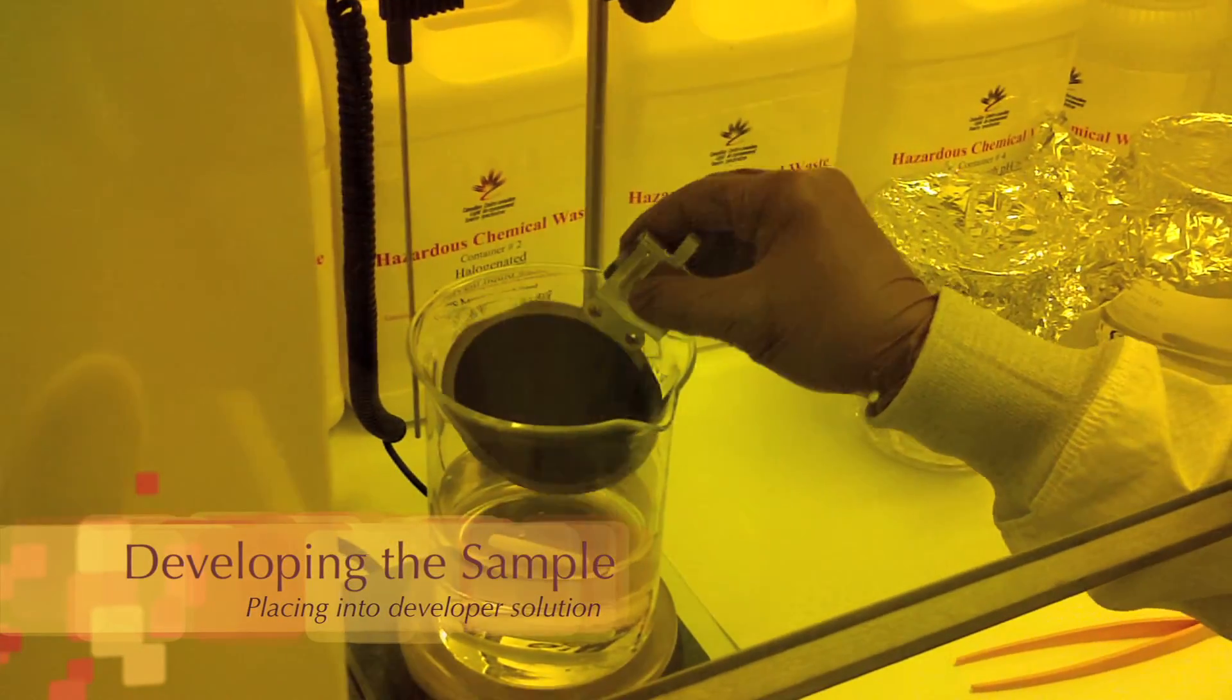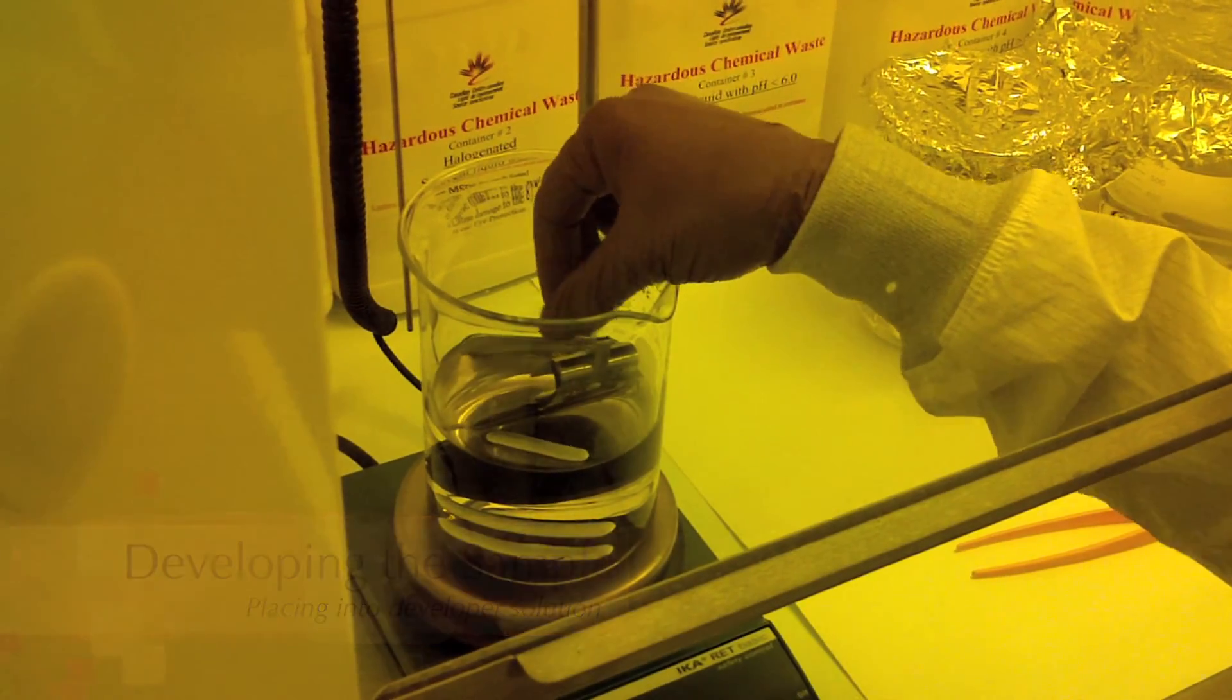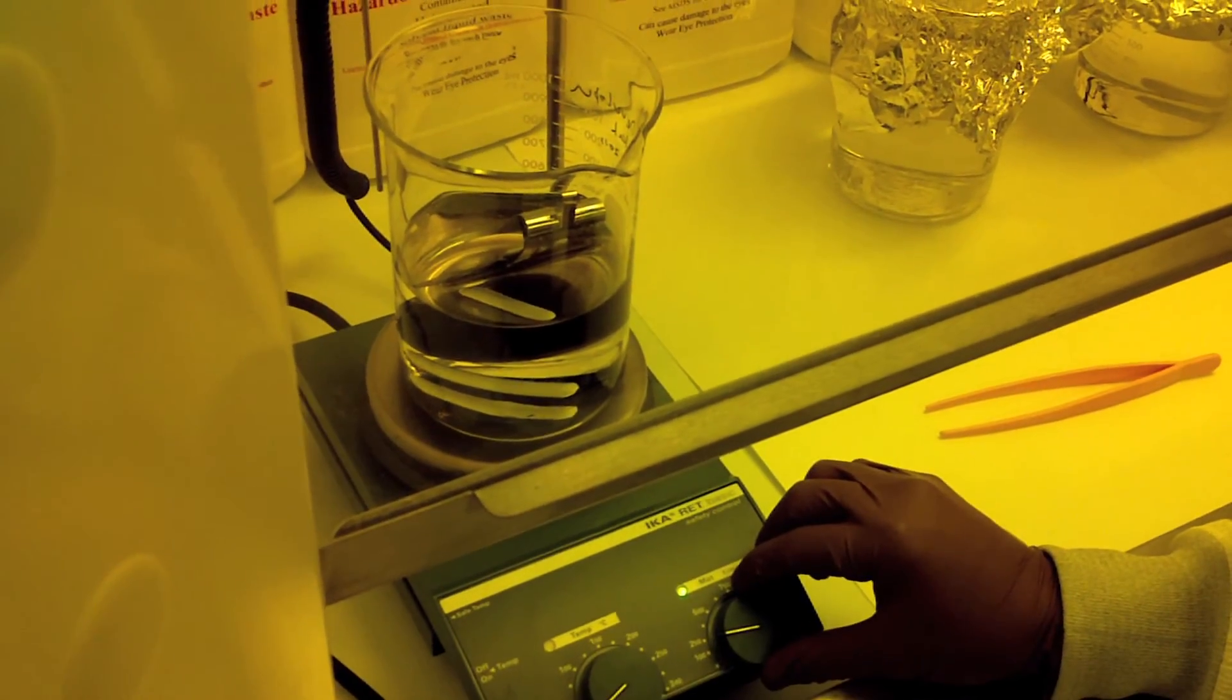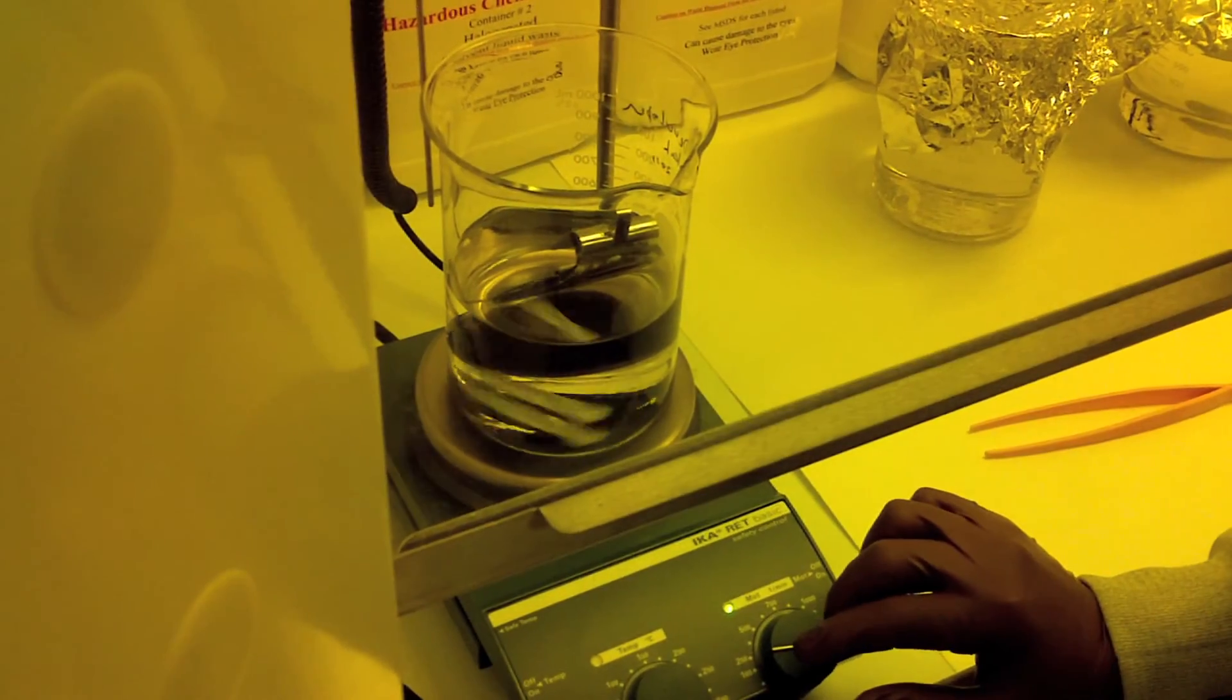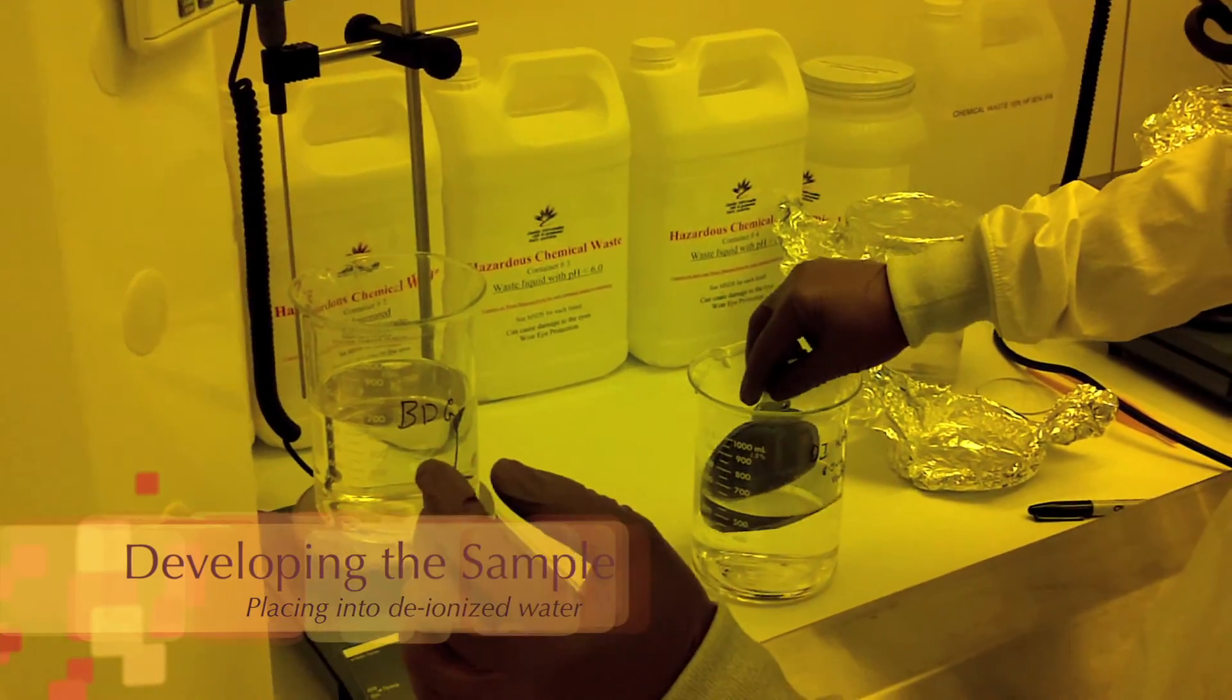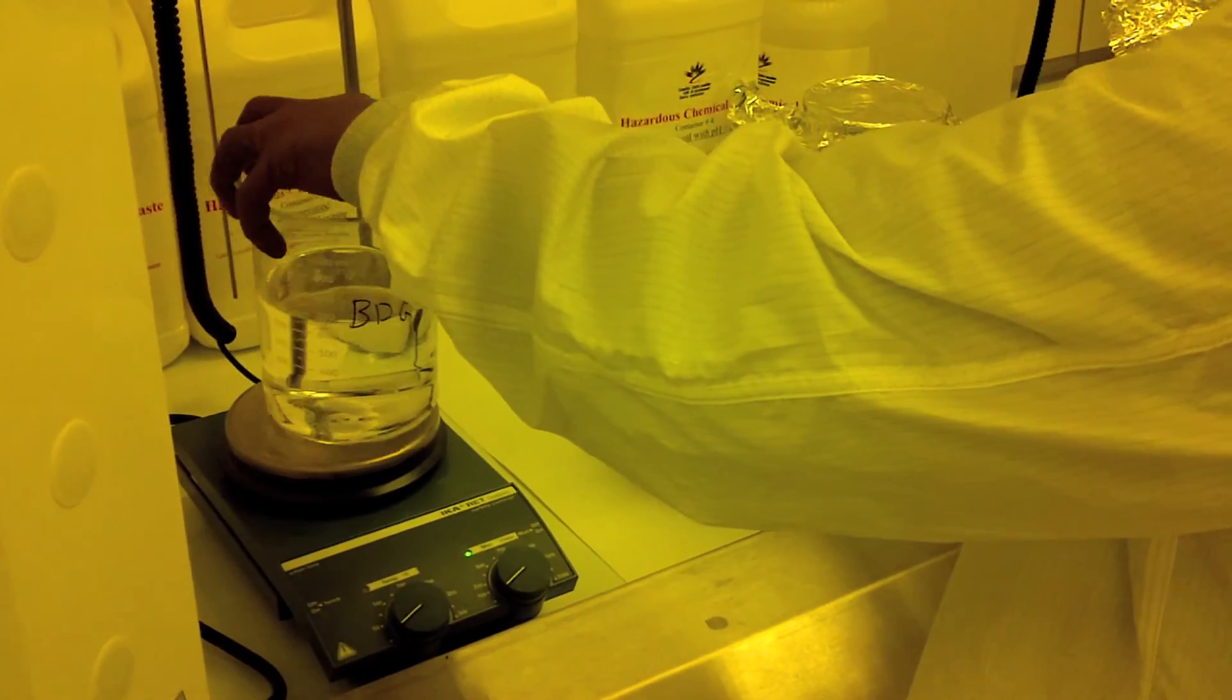Immediately after exposure, the sample is immersed in a premix developer solution to wash away the exposed areas of the resist to the X-ray beam. This process is time critical as the longer the sample sits outside after exposure, the harder it becomes for the exposed resist to be removed. The development process is finished by immersing the sample in a milder developing solution and finally in deionized water.